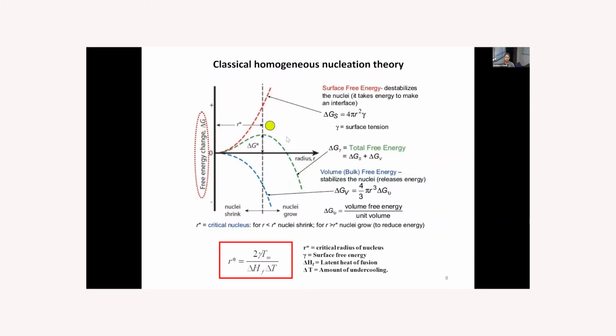So you can see it in green. First it's growing until it reaches the critical size of the nuclei, which is required for the nucleus to grow, and after that it drops. So it is the critical radius of the nucleus. It's inversely proportional to the supercooling temperature. That means that for the higher supercooling, this is lower temperatures, with a smaller radius we can induce the freezing.